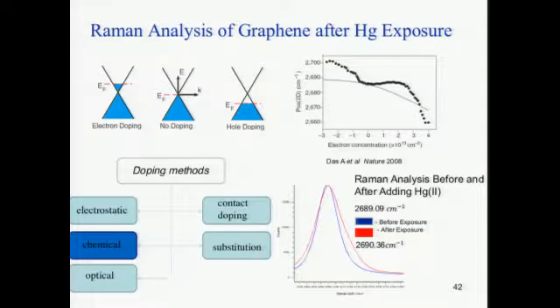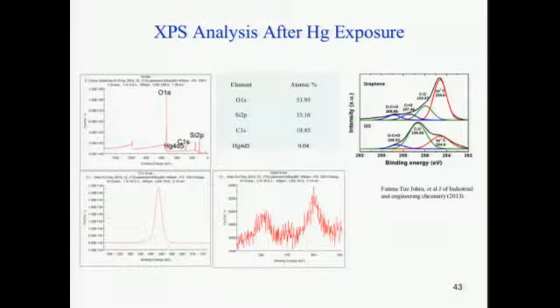We'd like to consider possibly some of the work that I described by Das in combination with that. And so using XPS, this is a scan of the XPS showing all the elements that are on the surface. And we can see here that we have the aliphatic carbon. This is after decoration. And we have the signature for mercury.